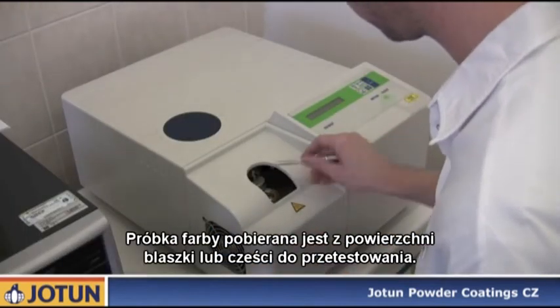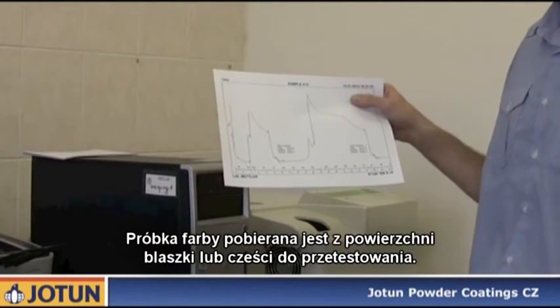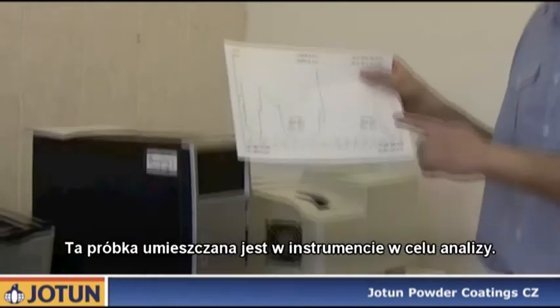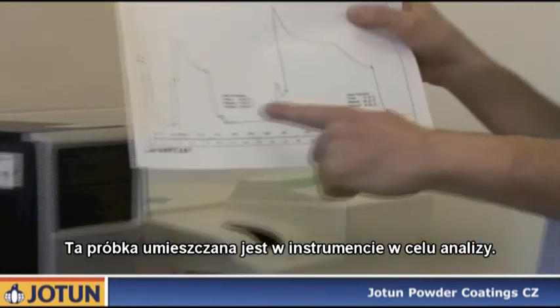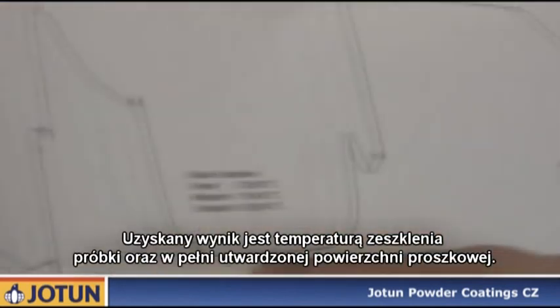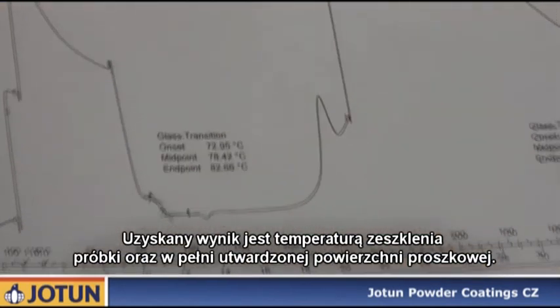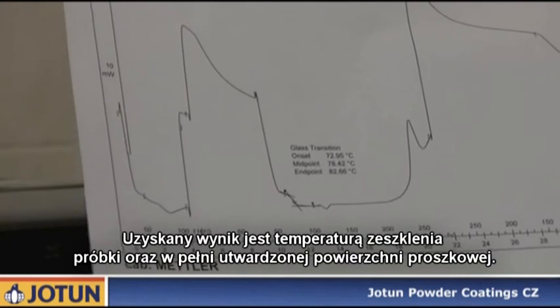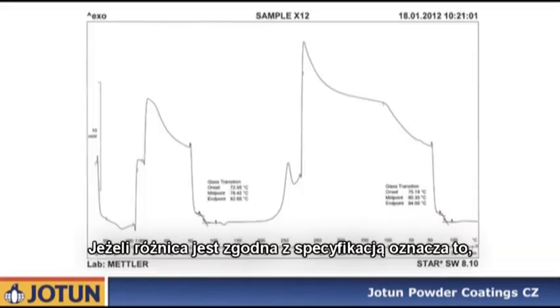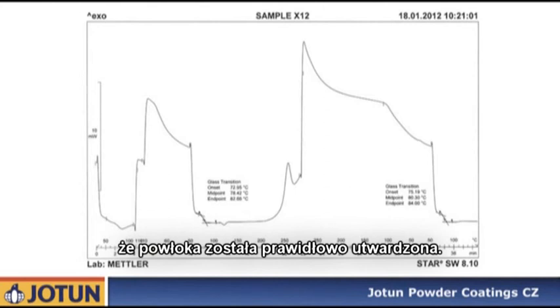A sample of paint is extracted from the surface of the panel or part to be tested. This sample is put in an instrument and analyzed. The results obtained are glass transition temperatures of the test sample and of the fully cured powder coating. If the differential complies with the specification, it means the coating has been properly cured.